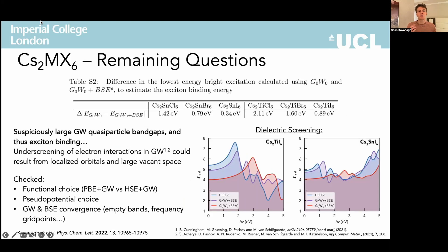Before wrapping up, there remain some questions regarding the quantitative theoretical modelling of the electronic structure of these compounds. Despite the GW plus BSE results revealing strong exciton binding and yielding absorption profiles in excellent agreement with experiment, the bare GW quasiparticle gaps and thus exciton binding energies remain suspiciously large. In GW studies on other materials, this has been attributed to underscreening of electron interactions within the random phase approximation, which could be particularly severe here due to the localised orbitals and large vacant space. Plotting the dielectric screening, the bare GW RPA spectrum is significantly lower than that of the hybrid DFT or GW plus BSE.